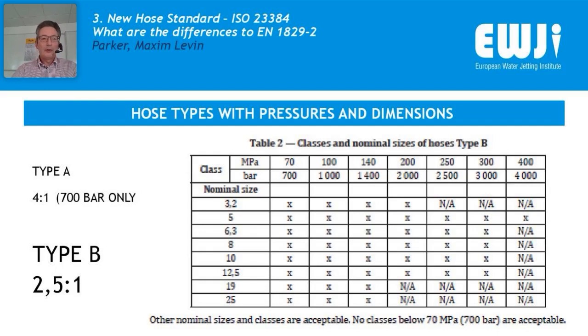All our products are type B hoses according to the new ISO standard, and they all have a design factor of 2.5 to 1, with the design factor lowering for higher pressure hoses. As you see, there are 7 pressure classes: 700, 1000, 1400, 2000, 2500, 3000 and 4000 bar. Does it mean that you will never get a 1500 bar hose? No, it doesn't mean that at all. These are just recommended pressure classes, and deviations are also acceptable. So it's no problem to get a, let's say, 15K hose or 20K or 40K.